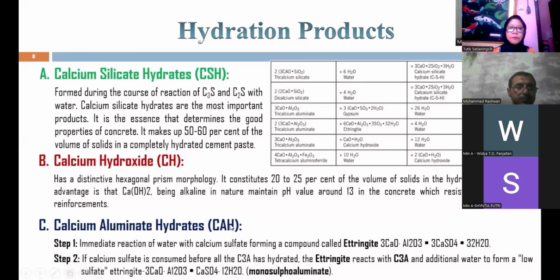After the reaction of the calcium sulfate with C3A, if the calcium sulfate, for example the gypsum, is already consumed in the first step but not all C3A is hydrated, some C3A is still present in the mix. The ettringite liberated from the first step will react with the remaining C3A in the mix, with the addition of water, forming monosulfoaluminate, or low-sulfate ettringite.